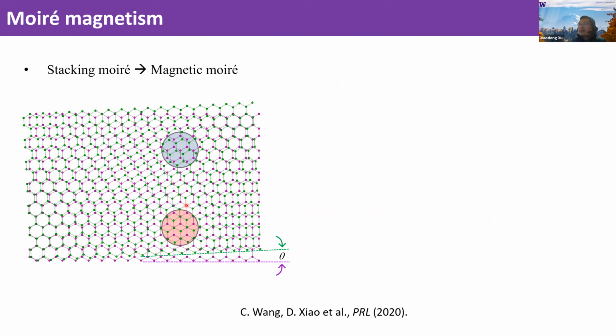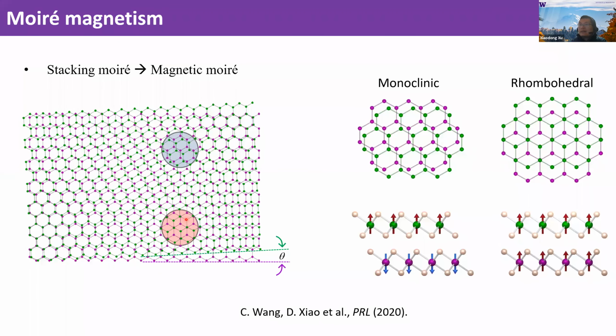On top, another monolayer of chromium triiodide. And naturally there will be local stacking order corresponding to monoclinic, and there will also be local stacking order corresponding to rhombohedral. So without doing anything, you would imagine forming a Moiré pattern, with part of the sample showing antiferromagnetic and part of the sample showing ferromagnetic. There will be domains, AFM and FM, alternating with each other. This is a very intuitive understanding of what a Moiré magnet looks like when you stack two monolayers of chromium triiodide on top of each other.